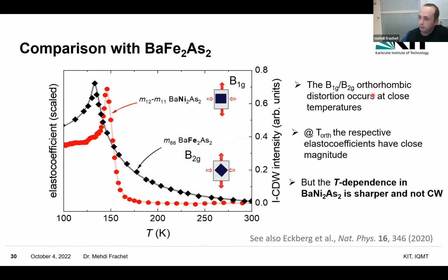The first one is that you see that the orthorhombic distortions, which belong to different symmetry channels in this nickel and iron compound, occur at quite close temperatures. So that means that we can make a comparison at the rotational symmetry breaking. You cannot see it from the graph, so you need to trust me because I have scaled everything. But if you look at the raw data, you see that the elastoresistance coefficients in the respective symmetry channels have quite the same magnitude. So really the amplitude of the effect is similar.